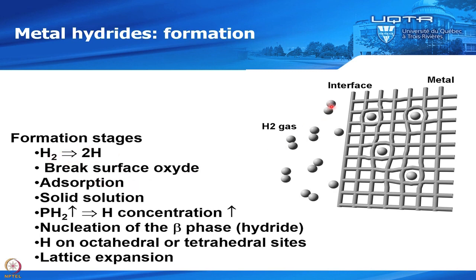And for hydrogen, first you have to be in adsorption, so you adsorb on the surface, and then it splits into atoms, and then the proton will enter the metal, and first it will form a solid solution, so it will just go into the metal structure. But as the pressure of the gas is increasing, the concentration of hydrogen in your metal will increase up until you nucleate the metal hydride phase. And in that phase, the hydrogen will go on specific sites depending on the crystal structure. It could be on the octahedral or a tetrahedral site. And you have a lattice expansion. It could be up to 30% of expansion of your lattice, of your metal.